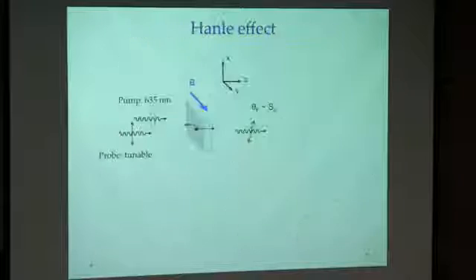Okay. So, I have been talking about this spin dynamics in terms of excitons, but experimentally, at the early stage, we did need experimental evidence that they are truly excitons. So we did the same kind of measurement, but in a steady state fashion. We use continuous wave lasers, not the pulsed laser. The pump laser is at higher energy, higher than the band gap energy, and it's circularly polarized light. And the probe light has a narrow wavelength, and it's tunable.